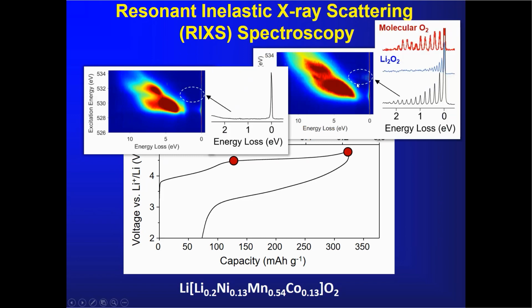I'm going to expand this region up, and you should see it now here. So this black curve is the expansion of this region here. This is the elastic peak at zero energy loss. And if you compare this with this RIXS spectrum for molecular oxygen, you'll see the same spacings. This is effectively a vibrational spectrum, and this is the vibrational spectrum of molecular oxygen. So it's a very precise fingerprint that shows you that there is molecular oxygen at the end of charge.